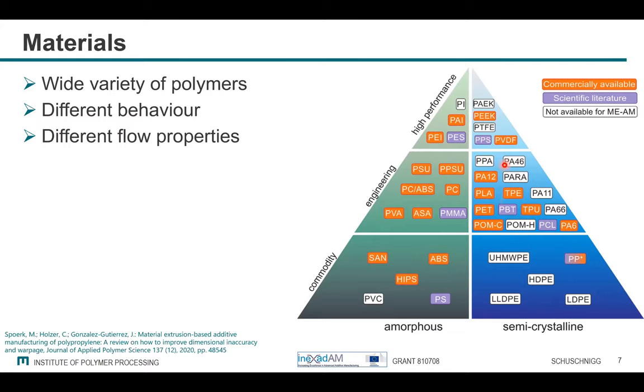But there are also other polymers used for additive manufacturing, such as polyamide 12, and then here at the tip we have the high performance polymers, high temperature polymers, polyetherimide, polyether ketone, and so on. Some of them are at this time used in scientific literature, but they are going to broaden the market for additive manufacturing materials. Some of them, for example HDPE and LDPE, we tried to print, but the problem was, due to the PVT diagram and the semi-crystalline behavior, the shrinkage between the processing temperature and the cooled down state led to not good prints.